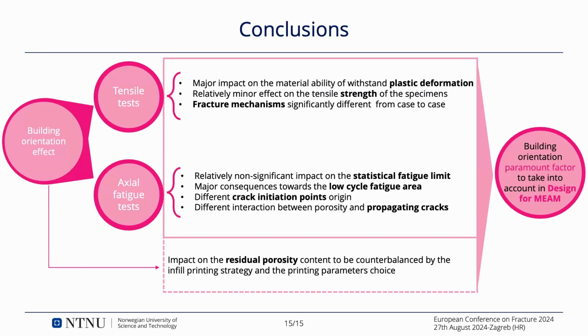And summing up the results of this investigation about building orientation on material extrusion additive manufacturing, about tensile tests, the major impact is on the ability of the specimens to withstand the plastic deformation and on the fracture mechanism. And for the axial fatigue tests, the same, the fracture mechanisms are affected by the building orientation, while the fatigue limit itself is not so significantly impacted. On top of this, we also realized that the building orientation affects the residual porosity, apparently. So this needs further investigation, and this is an issue that needs to be counterbalanced somehow.